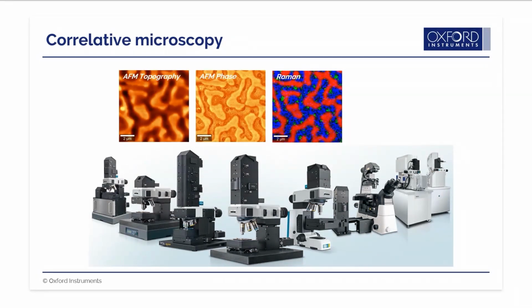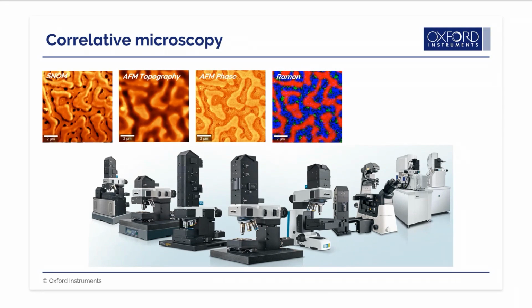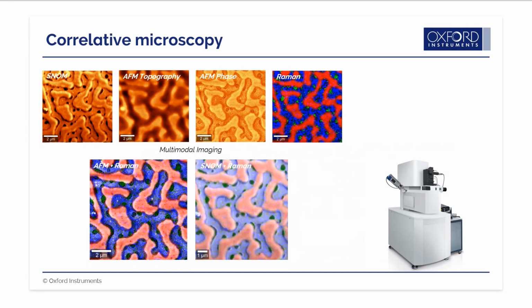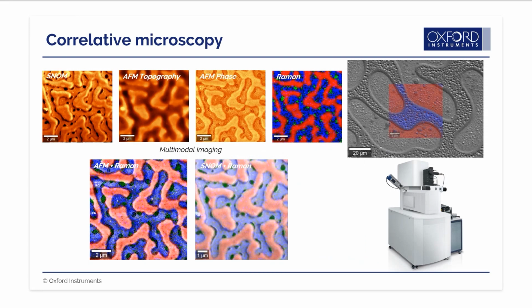The topography and phase images reveal the fine structure of this polymer blend, whereas the SNOM image shows the transparency of the blend. Interestingly, the thinnest layer, the acrylate, appears non-transparent because it does not contain the styrene block, which acts as a little lens. The latest combined instrument is the RISE microscope, where Raman is integrated into the vacuum chamber of an SEM, allowing for high-resolution structural images in combination with EDS, EBSD, and all the other techniques where the electron beam is required.